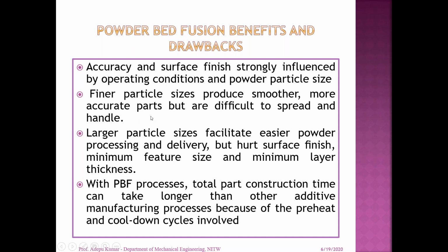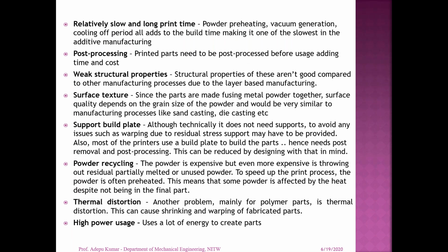Finer particle sizes produce smoother, more accurate parts, but are difficult to spread and handle. Larger particle sizes facilitate easier powder processing and delivery, but hurt surface finish, minimum feature size and minimum layer thickness. With the PBF process, total part construction time can be longer than other additive manufacturing processes, because preheat and cool down cycles are involved, so it takes a lot of time to complete. Then relatively slow and long print time, post processing required, weak structural properties, surface structure, support build plate and powder recycling, thermal distortion, high power usage. These are the drawbacks of the powder bed fusion process.